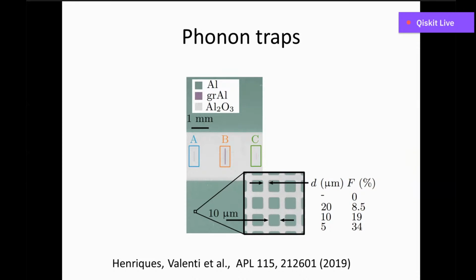What I show here is an implementation of phonon traps with the circuit that I've illustrated before. Again, our three granular aluminum strip lines sitting on a sapphire substrate and surrounded by lower gap aluminum. We pattern the lower gap aluminum, the trap, as a square lattice of square aluminum islands, 10 micrometers in size. And we fabricate four different samples by sweeping the pitch, the lattice constant of this structure, obtaining different packings, different coverage of phonon traps on our substrate upper face. And we also fabricate a control chip without phonon traps to assess the strength of phonon trapping.